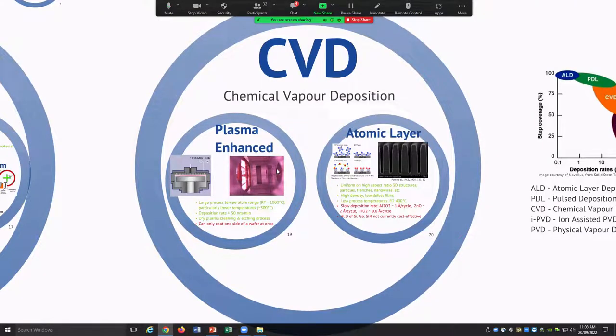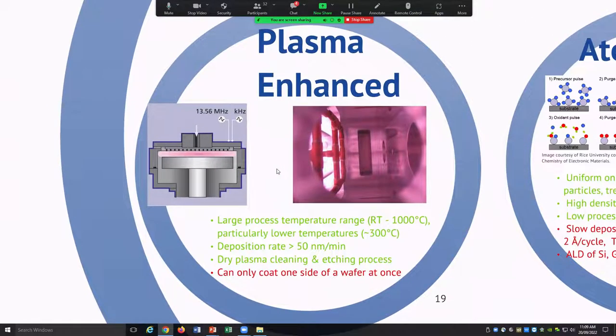Another refinement, available in other nodes within ANFF, is chemical vapor deposition. I did mention plasma enhanced chemical vapor deposition is one variant of it. Another one is atomic layer deposition. I'll go to plasma enhanced first. Here you're typically using more organic liquid precursors to create a coating. It's widely used in the semiconductor industry for doing silicon dioxide, but can be used to create organic polymers as well. So you can polymerize monomers using chemical vapor deposition. You can get a high deposition rate. For some systems, you can only coat one side of the wafer. Other systems, you can coat both sides three-dimensionally.